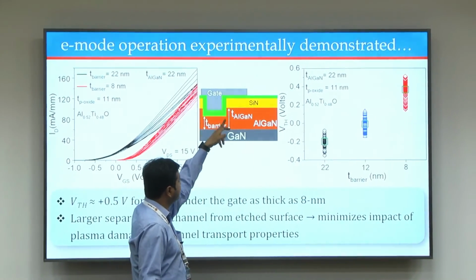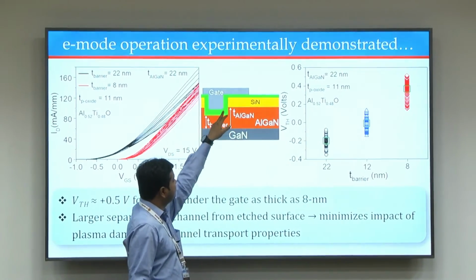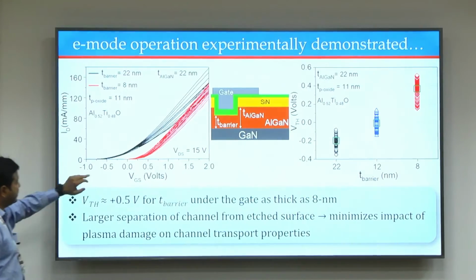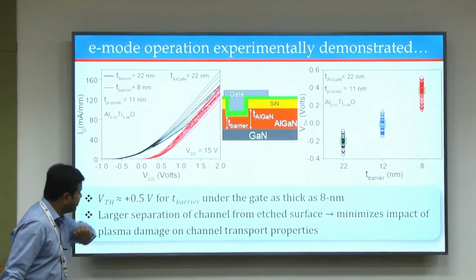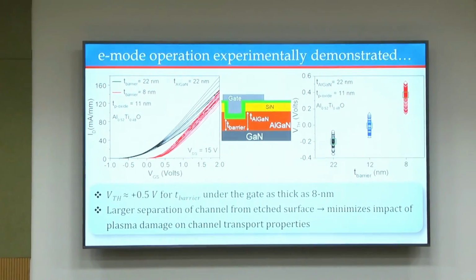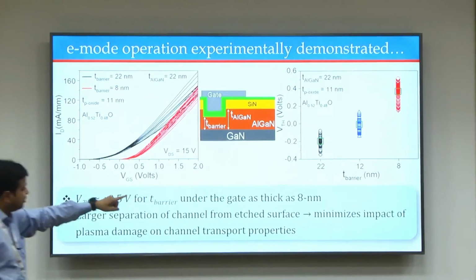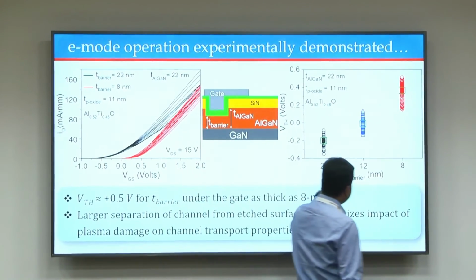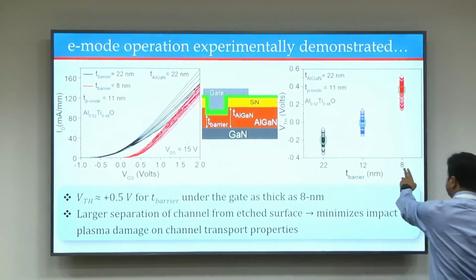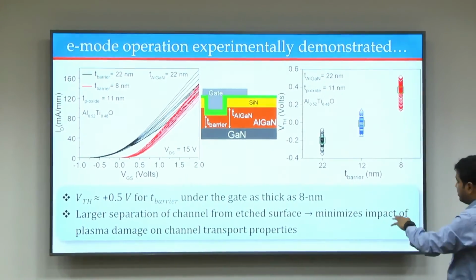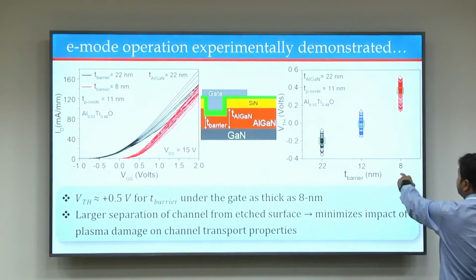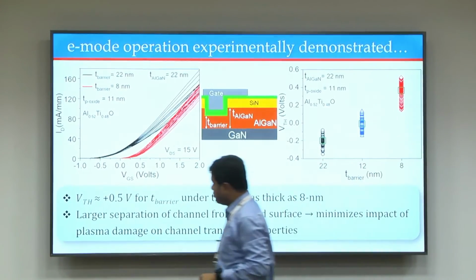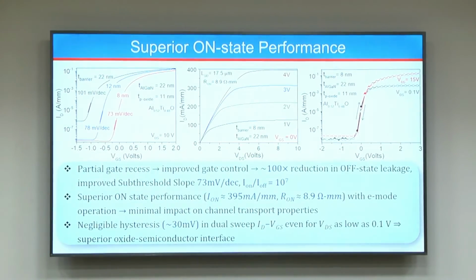So you're not fully removing the 22 nanometer of AlGaN, you're only partially removing AlGaN here, and that gives you a further shift towards positive threshold voltage, right? So if you see on the other side, now if you recess from 22 nanometer to 8 nanometer, you are still too far from the 2DEG, which may affect the leakage. You are now in the positive threshold voltage regime, right?